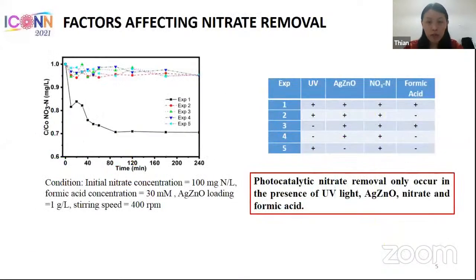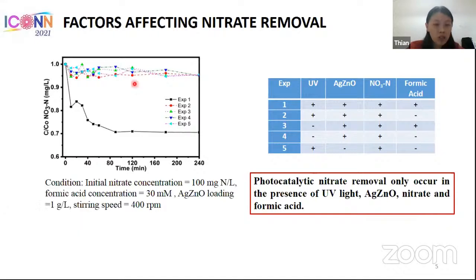So the first thing that we did is we tried to study what are the factors which affect this nitrate removal. So from the graph here, we can see that it is very clear that photocatalytic nitrate removal only occurs if we have UV light, if we have a photocatalyst in the presence of nitrate, and also formic acid as the hole scavenger. So in the absence of any one of these elements, photocatalytic nitrate removal will not happen.